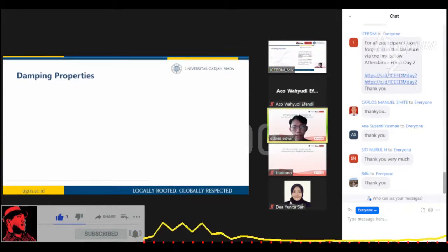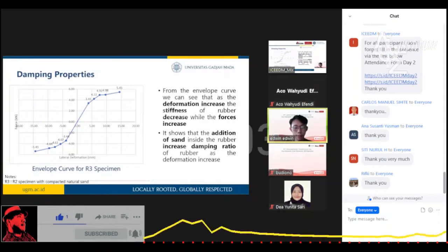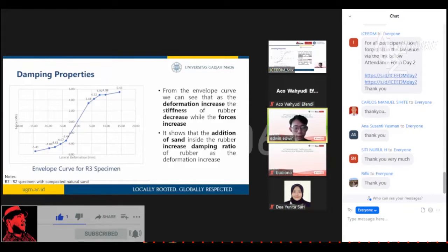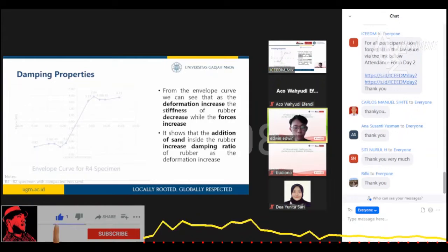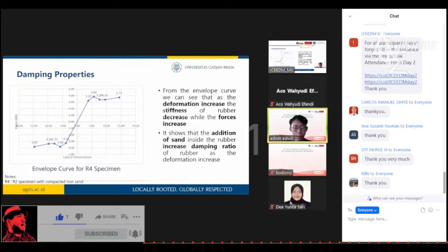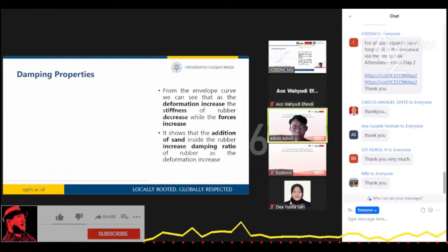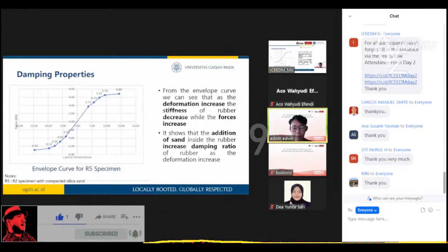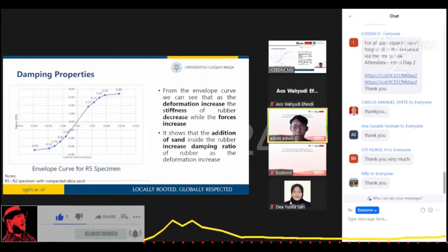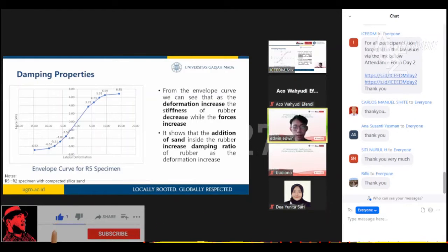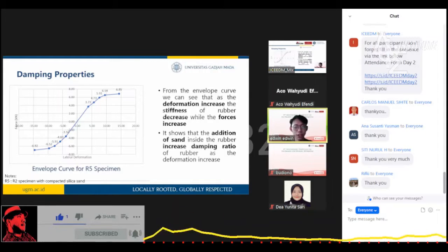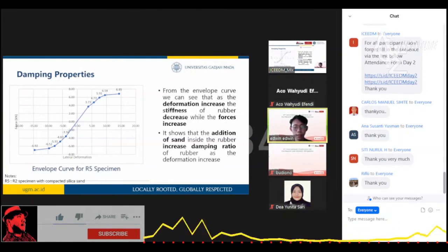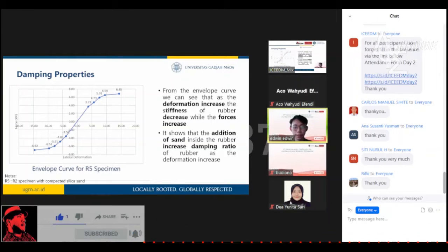And this is the example of envelope curve for R3 specimen. And this is the envelope curve for the R4 specimen. And this is the envelope curve for the R5 specimen. And from the envelope curve, we can see that as the deformation increase, the stiffness of the rubber decrease while the force increase. It shows that the addition of sand inside the rubber increase the damping ratio as the deformation increase.